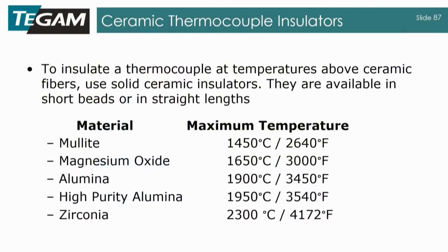So what the industry has come up with as a solution to this is they make these ceramic tubes, and the ceramic is going to be mixed with one of these materials depending on the maximum temperature that you're trying to measure. And the way it works is that you basically take your immersion probe, you slide it into this ceramic sheath, and then you put the whole kit and caboodle into the thing that you're measuring. The idea of the ceramic is that it passes through the temperature so that you can measure the temperature, but then it's protecting the material of your probe. In many cases, it's stainless steel. This way, you can get up to a higher temperature with stainless steel, and for things that start to corrode stainless steel, which I recently found out with a customer, boiling aluminum.